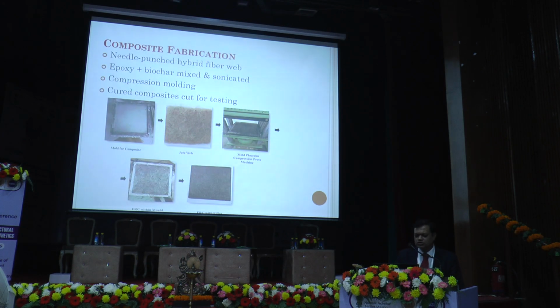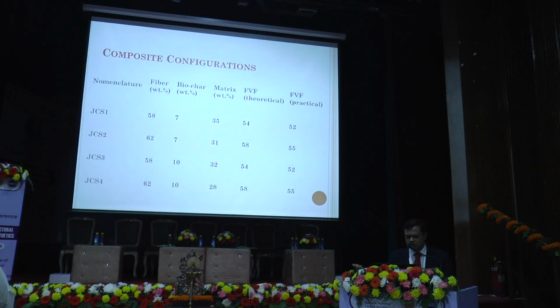This is the composite fabrication that was made with a compression molding machine. Needle-punched hybrid fiber web was prepared in the card. Then epoxy and biochar were sonicated and applied on the compression molding machine. Cured composites were cut for different testing conditions.